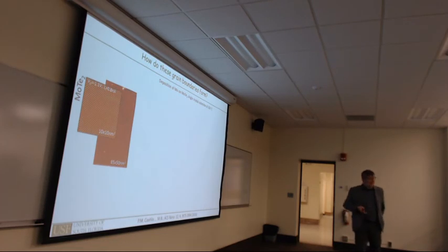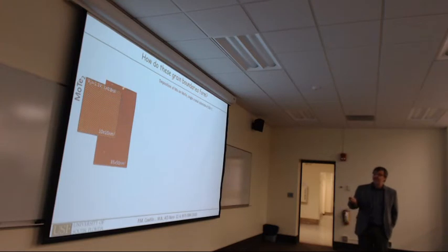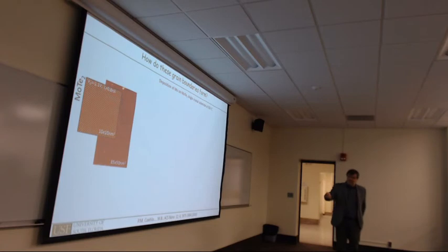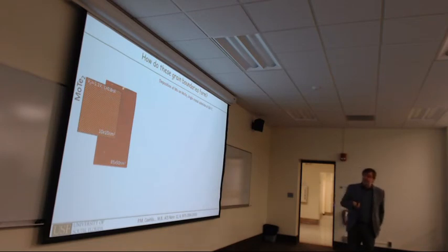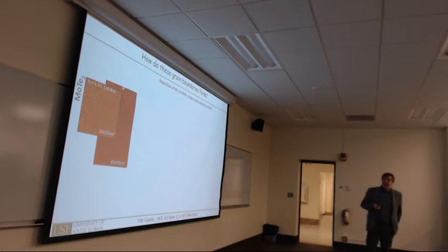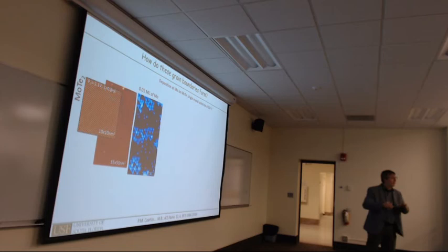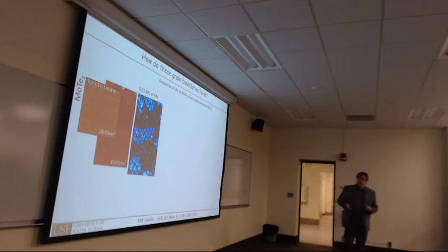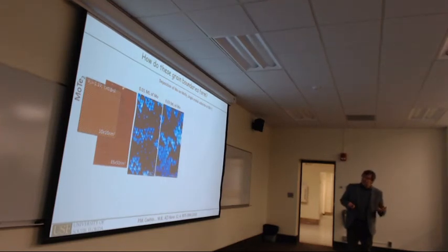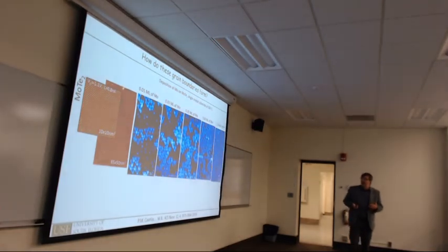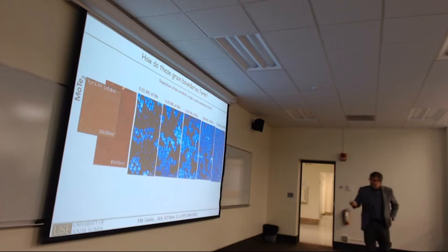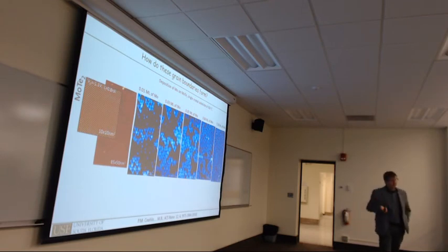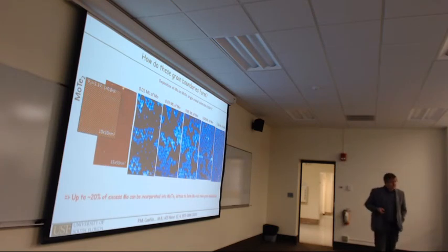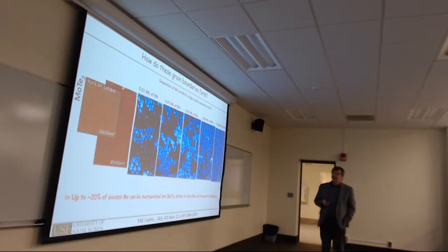Right. So to test that, that's very easy to do. You start with a single crystal molybdenum ditelluride in this case, which has no grain boundaries to start with, and then you vapor deposit molybdenum from an evaporator in ultra-high vacuum on the surface, and provide some kinetic energy by some temperature, and see what happens. So we just deposit molybdenum, and really start forming these triangular loops due to the incorporation of excess molybdenum. For molybdenum ditelluride, you can add more molybdenum and more molybdenum, and you cover the entire surface with these twin grain boundaries. You can get up to 20% of excess molybdenum in the monolayer in molybdenum ditelluride in this way, just by vapor depositing molybdenum on a single crystal surface.